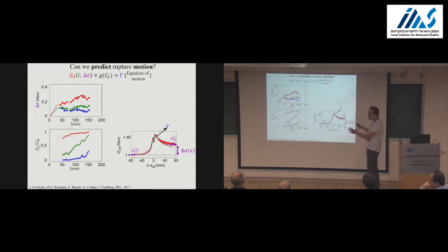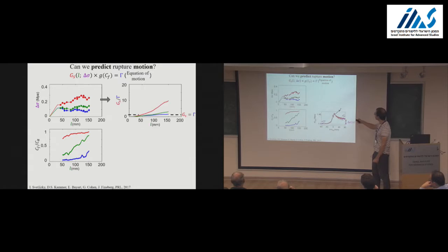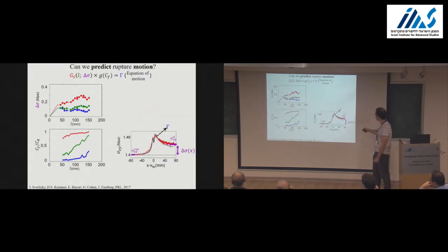So this is the direct mapping between frictional rupture fronts and the free crack face in brittle cracks. But the residual, you subtract what you measure as the sliding velocity of the tail? Yes. Or you fit it? No, we measure it. I measure the pre-stress, I know the residual stress, I subtract it, and I define the stress drop. And all calculations are based on this stress drop.